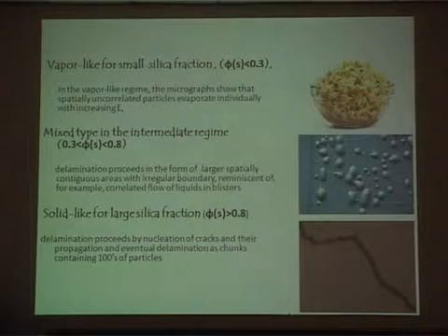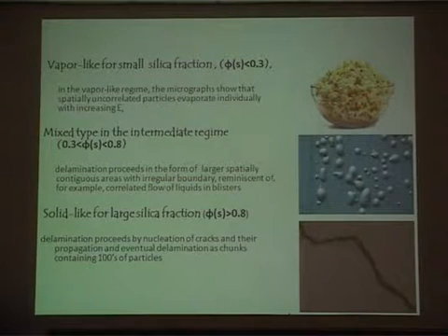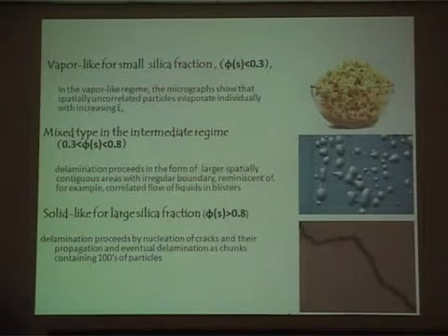So you can have small blisters. This is not the image. This is just to say what nature would look like. And if I have large volume fractions of silica, which is greater than 0.8, you essentially have linear cracks and the system fails like really rigid objects.